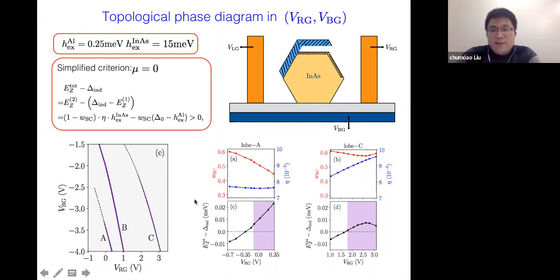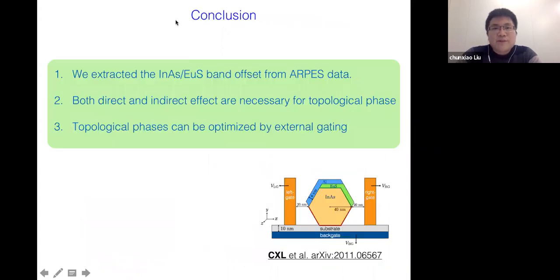So all right, that's the end of this talk. To conclude, in our work, we extracted the indium arsenide europium sulfide band offset from ARPES data, and the value is in between aluminum and vacuum, and it helps the electron accumulation near europium sulfide. And second, we find that both direct and indirect effects are necessary for realizing topological phase in realistic devices, and the topological phase can be optimized by external gating. Okay, thank you for your attention.